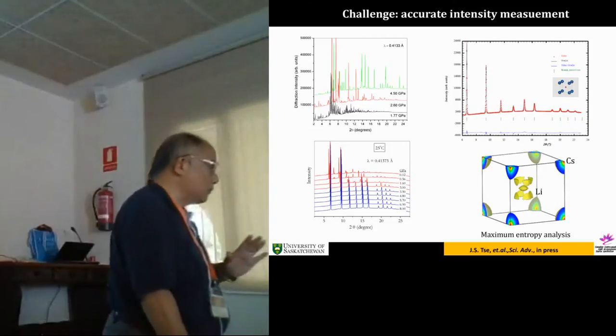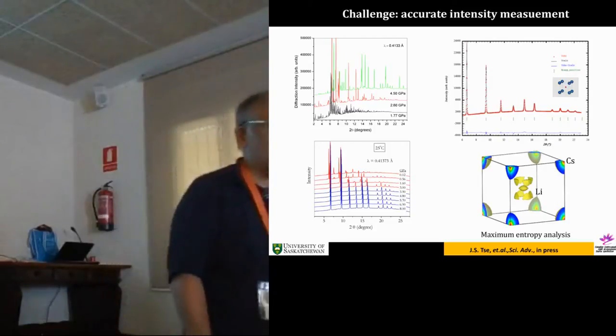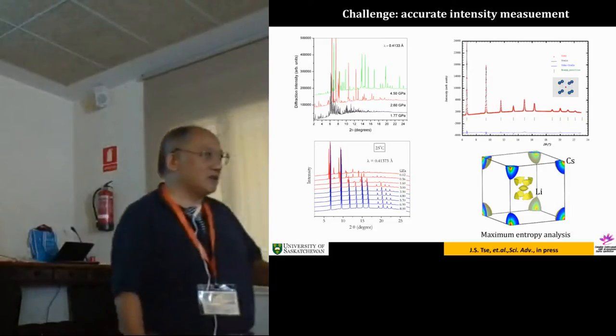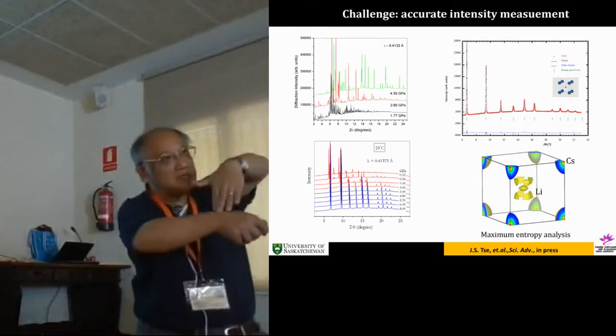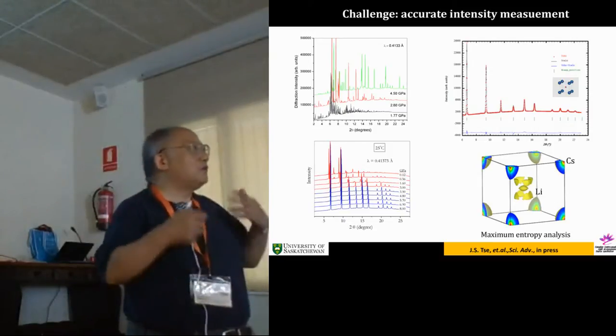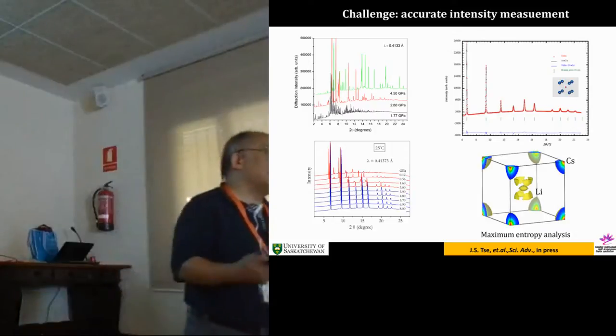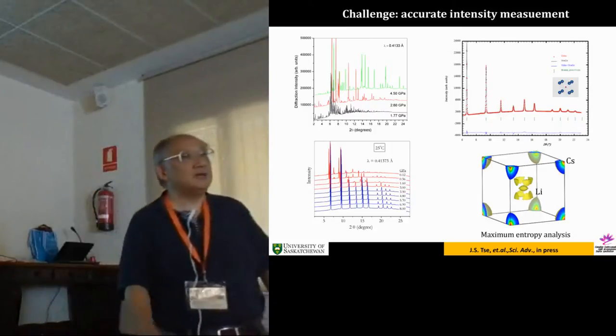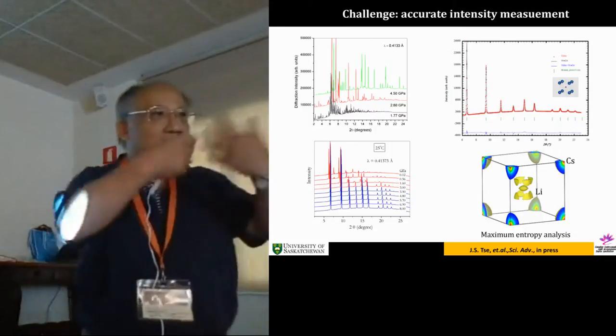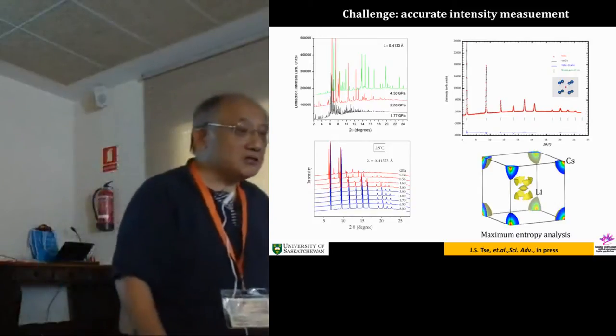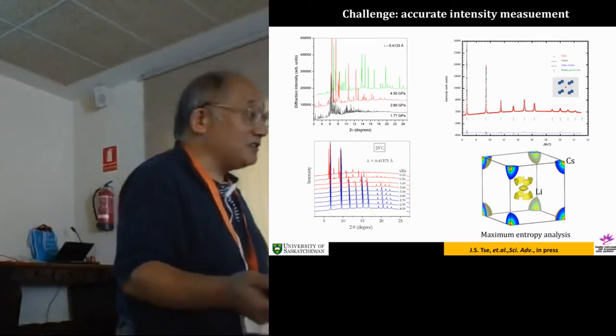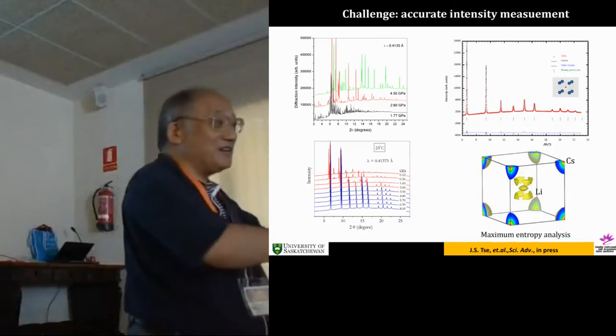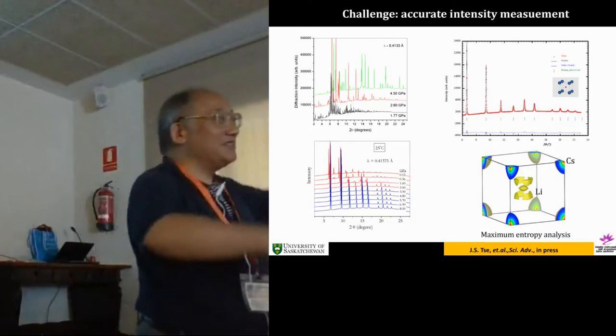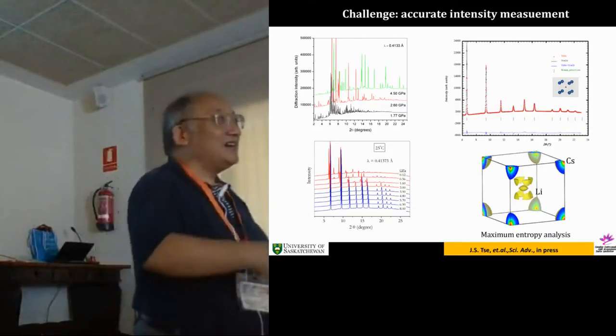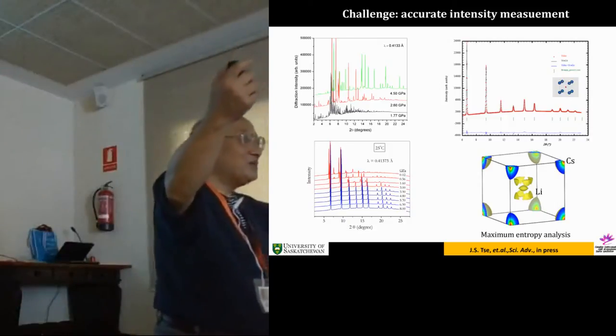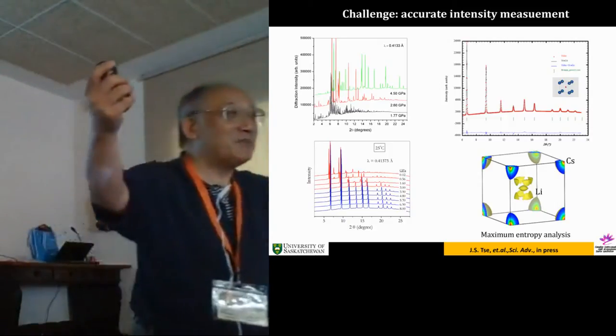If you go to most discussions, the metallization of germanium and silicon is due to the d band coming down and touching the valence band. But we find that the mixing is already there at 7 GPa, way before the transition. In hindsight, it's not difficult to understand because the thing doesn't go abruptly. It has to come down and come down. And electron, in a single determinant, of course, the electron doesn't go up there.